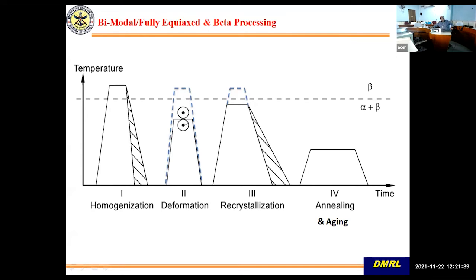But if you want a bimodal structure and want to refine the grain size, you deform in the alpha plus beta regime and then carry out recrystallization and annealing again in the alpha plus beta regime, and then final aging or annealing much lower down to get higher strengths.